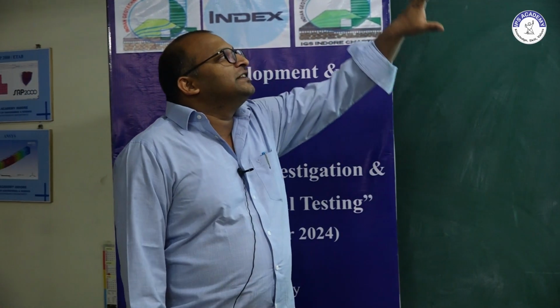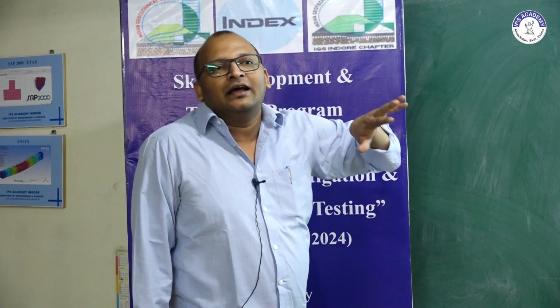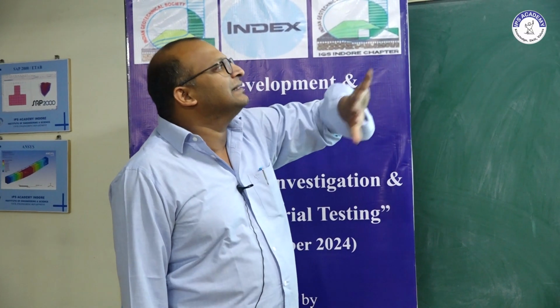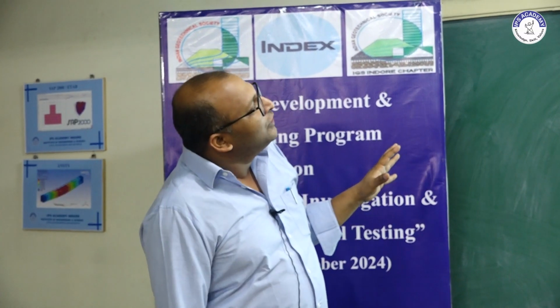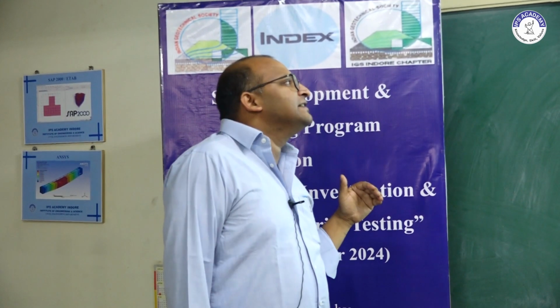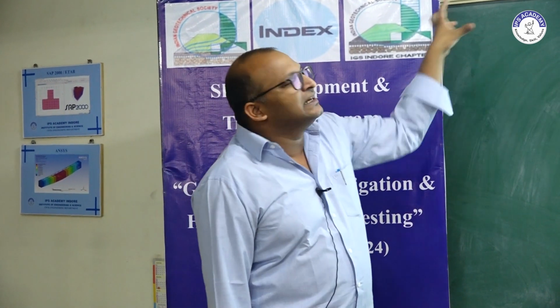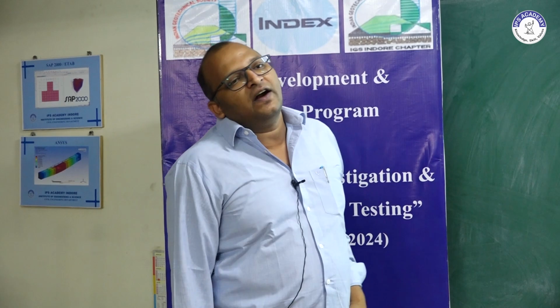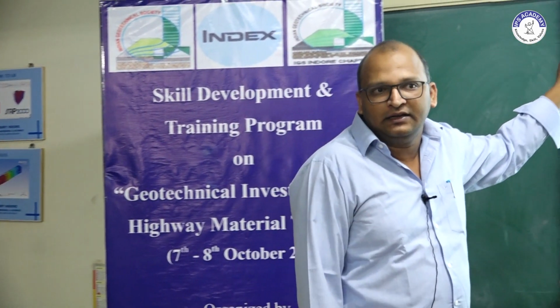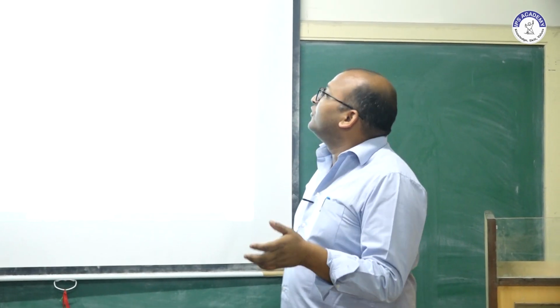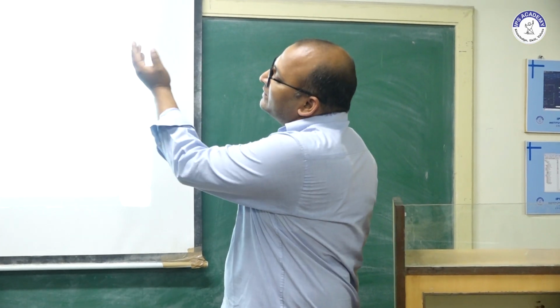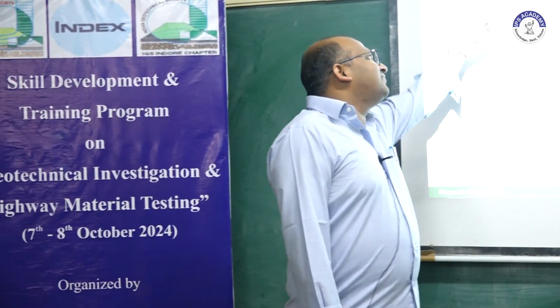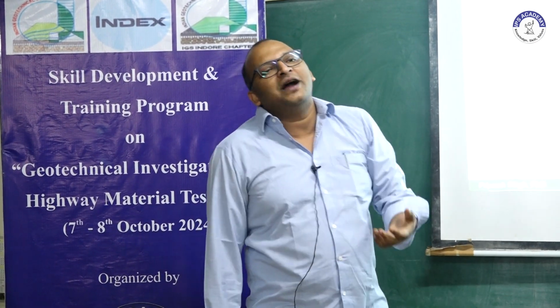And if you look at the composition of binders, by SARA analysis we can see what composition your binder has. It has saturates, aromatics, resins and asphaltenes. The major component in asphalt binders is the aromatic content, which may be around 50 to 65%. The least content, around 5 to 20% or 20 to 25%, is saturates and asphaltenes. And asphaltenes is the material which gives your binder the black or gray color.